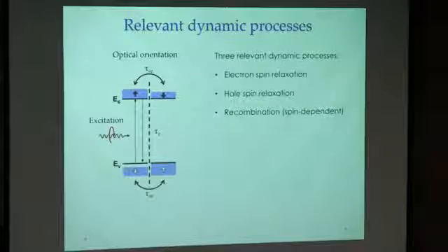So I would like to summarize the relevant dynamic processes in our ultrafast optics measurement, before I have no time to come back to this. Here, after we excite with circularly polarized light, we basically create spin imbalance in both the conduction band and valence band. Then there are three relevant processes. Electrons can flip their spin, or it's not really pure spin states, but the states relax, and holes can flip their spin. And also there could be recombination.